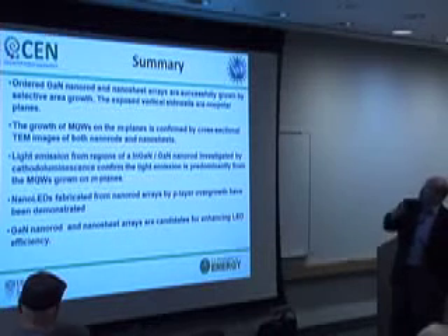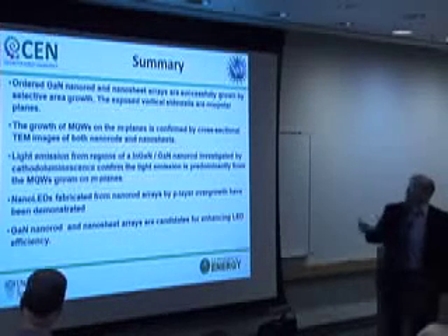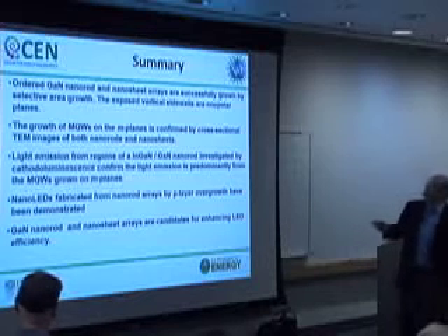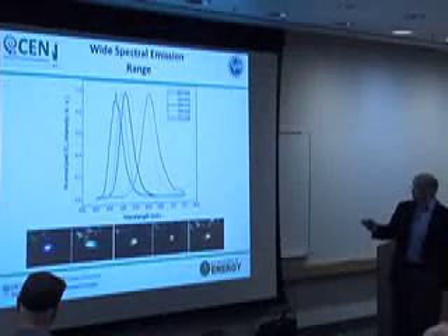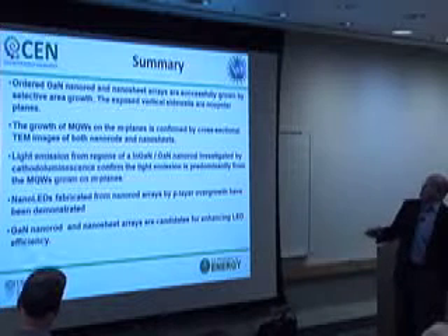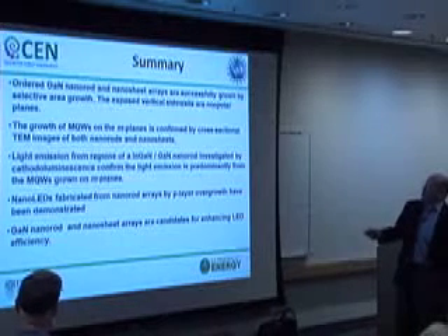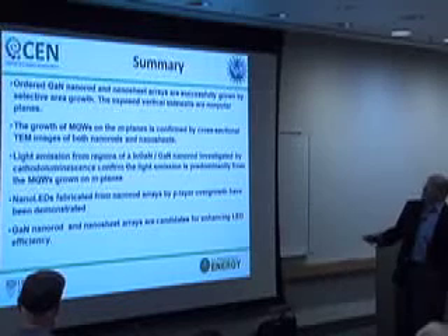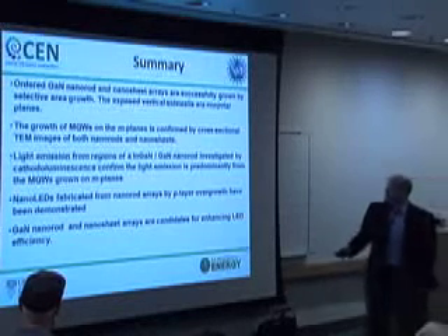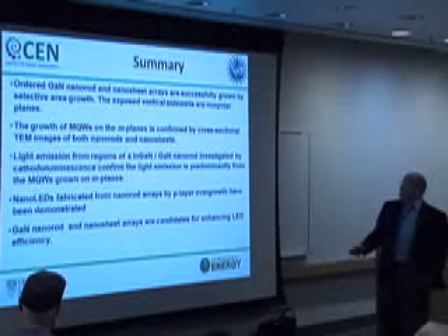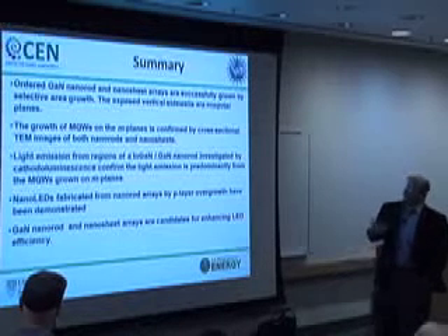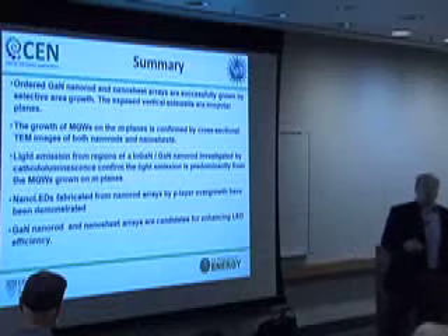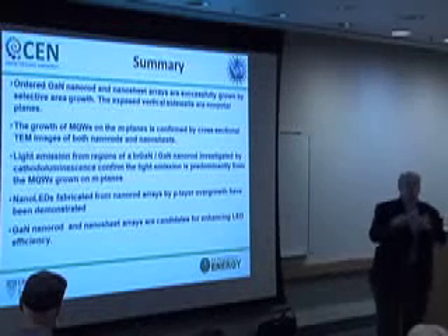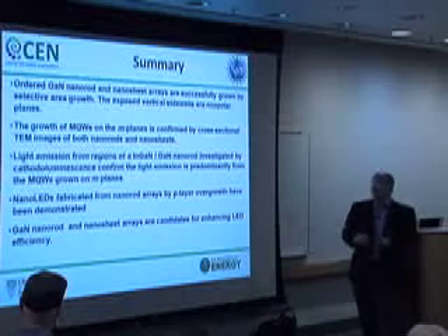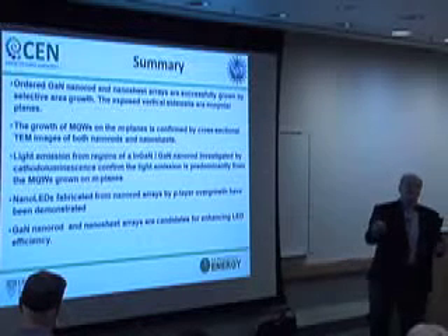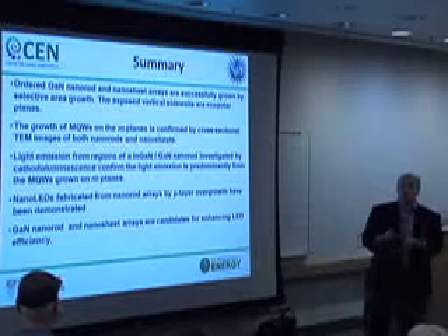Okay, so summarizing, the gallium nitride nanorods are successfully grown. The growth of quantum wells on end planes is confirmed, and the light emission is predominantly from the end plane, not the sidewalls. We're looking forward to getting more rigorous measurements on these structures and finding out whether in this geometry we get a distinct advantage. That will involve measuring absolute efficiency of the devices, which we haven't done yet. We're still measuring relative efficiency.